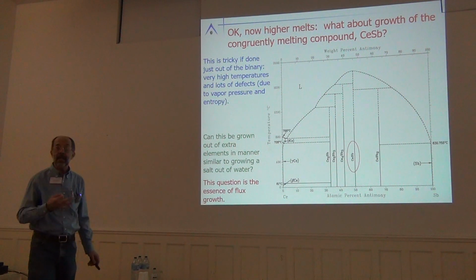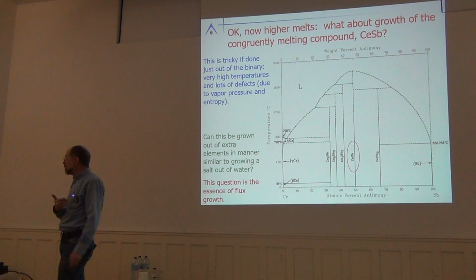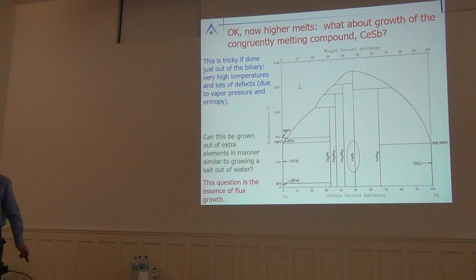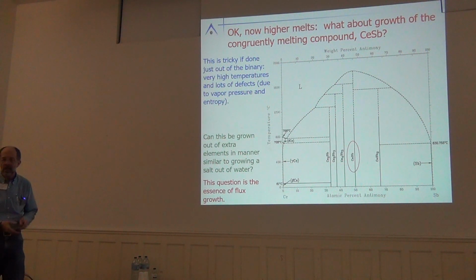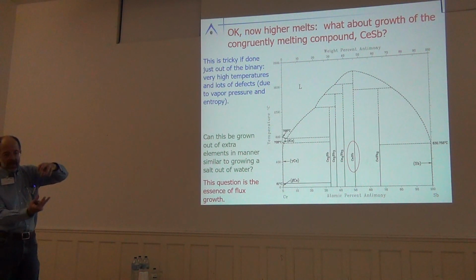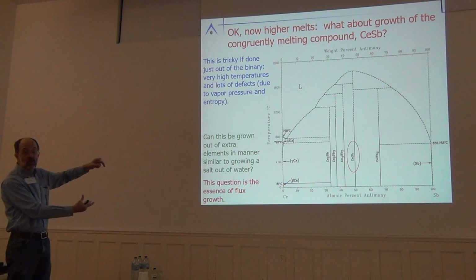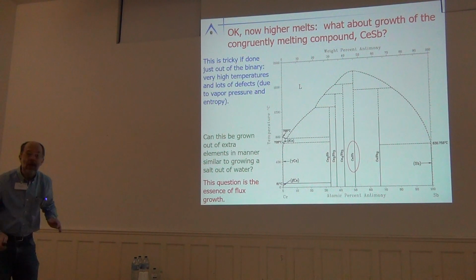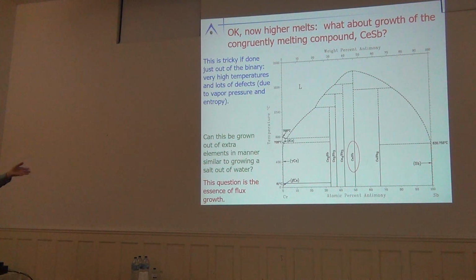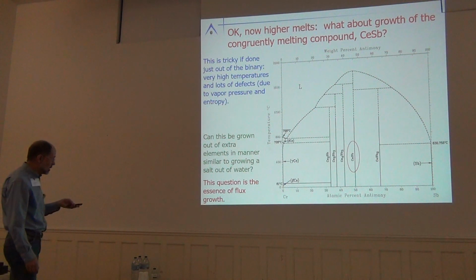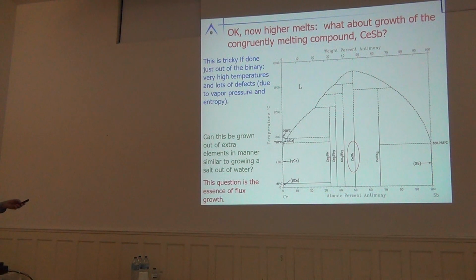Now, Hulliger and Vogt at ETH Zurich did grow this in the 60s and 70s by a process they called mineralization. They basically took cerium and antimony, sealed it into a steel tube, put it into a furnace, ran away and covered their ears, and hoped it didn't explode. And they did get nice crystals, okay? But they did have a degree of disorder. Now, you can do it that way, but it's not the easiest way, okay? There are other ways of doing this.